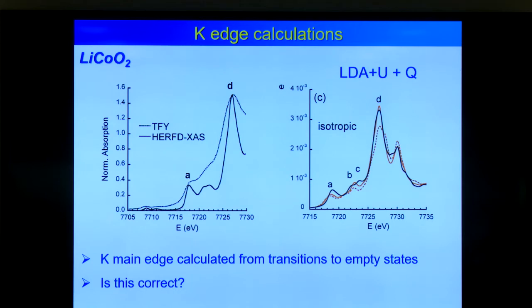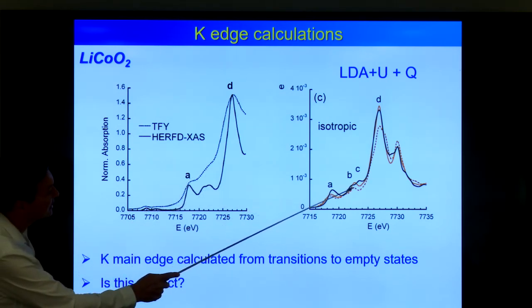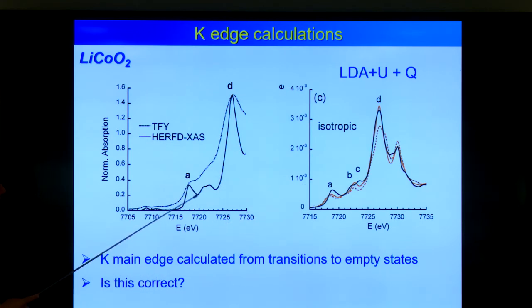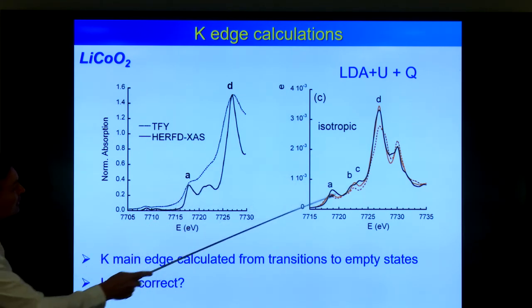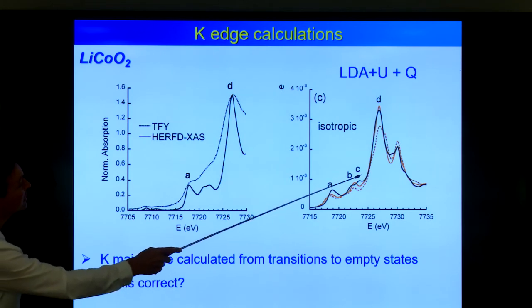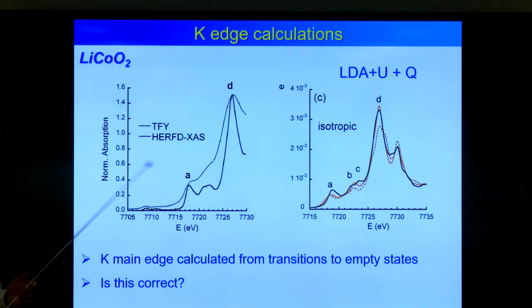The K edges are normally calculated by transitions to empty states, so by density functional calculation. This is a calculation we did for lithium cobalt oxide, and if you compare the experiments, so this is normal X-ray absorption, high resolution X-ray absorption, and this is the calculation with core hole lifetime adapted to the high resolution one. You get a quite reasonable description of all the features and the calculation comes back in the experiment. But the question is, is this conceptually correct?